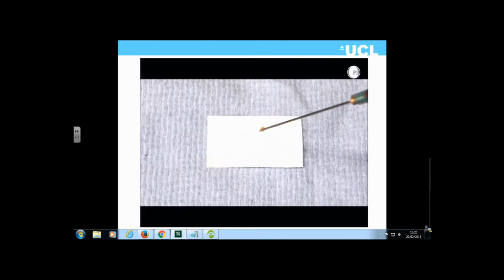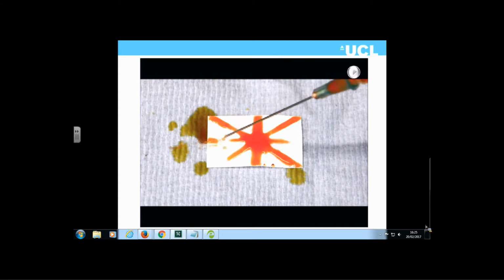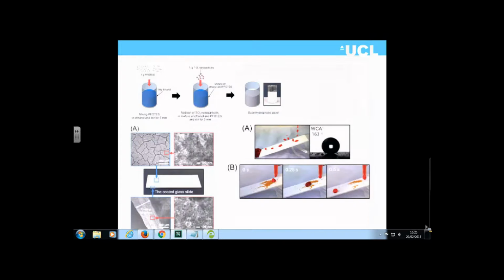We've also developed systems where you can raise water up, similar to what plants do, using the superhydrophobic system. Similarly to capillary action, you can raise water by about 4 to 5 centimeters. This is our pre-patterned shape, and you see the water will wet some parts but not others, giving distinct patterns so water flows in particular directions or channels, with a superhydrophobic surrounding but a non-superhydrophobic middle part.